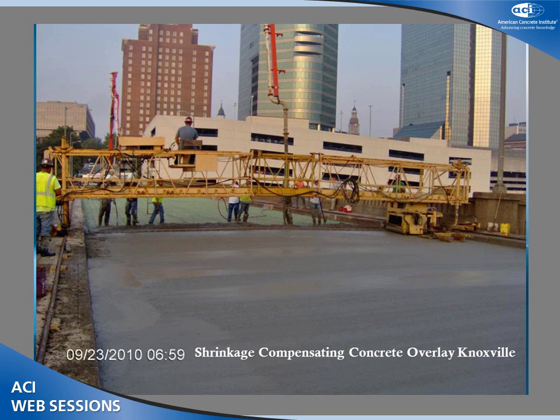Well, in Knoxville, Tennessee, several years ago, we did an overlay on a viaduct that was a very, very major and very high-profile viaduct that takes you down to what they call the Museum District. And this was done over a bridge that was actually built probably around 75 years ago. The concrete that was put in here was a shrinkage-compensating standard mix design. Again, we were using the standard mixes that we would use like in Ohio and Michigan, about 100 pounds of components, 600 pounds of Portland cement. They placed this with a concrete pump. It was 4 inches thick, and it's provided a very adequate wearing surface.